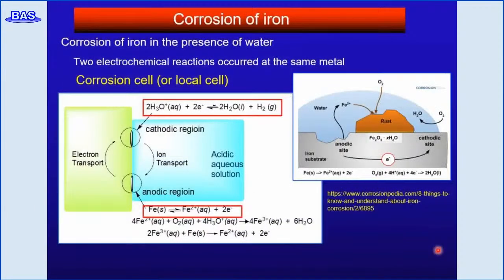In most corrosion events, the oxidation of metals in the presence of water takes place through two electrochemical reactions, both occurring at the same metal-aqueous solution interface, as shown in this scheme. There are two electrodes, one anode and one cathode, located almost adjacent at the junction of electron and ionic conductors. On the surface of iron, for example, iron dissolves to iron(II), which reacts with oxygen to form iron(III), which precipitates as iron hydroxide or iron oxide.